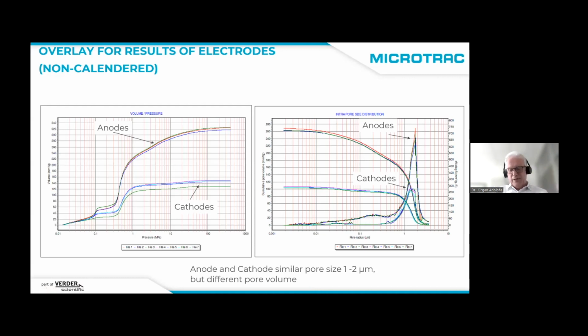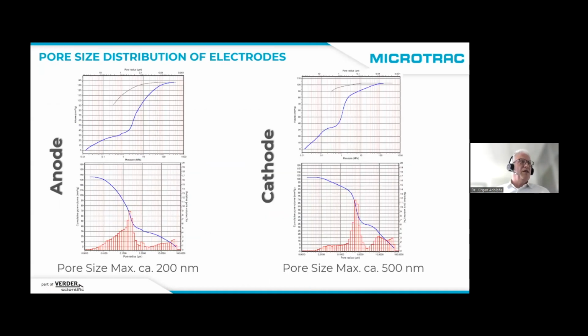This is one of the results we get, for example, from this mercury porosimetry. Another example, again, we see here an anode with pore size maxima in the range of about 200 nanometers with a second maximum, and a cathode, for example, in a range of about 500 nanometers. So these are typical results you can get from mercury intrusion porosimetry.